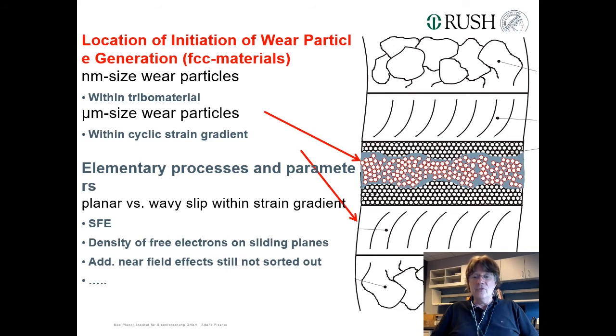I'm still looking for somebody. But at first hand, you can just read fatigue papers. The best thing would be multi-axial fatigue papers and see whether there is a material that stays under planar sliding conditions, no matter what cyclic plastic strain takes place. And this should bring about, within the FCC group, smaller wear rates because it generates nanometer-sized wear particles. Pretty simple.